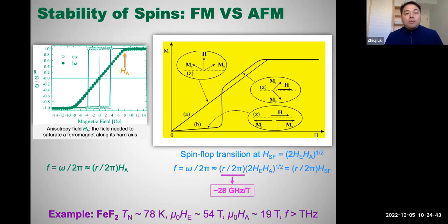If we look at this simple comparison between ferromagnets and antiferromagnets, for ferromagnets, the characteristic spin dynamics frequency, the so-called FMR frequency, ferromagnetic resonance frequency, is around gigahertz. It's simply gamma times H_A, where gamma is the gyromagnetic ratio, and H_A is the anisotropy field. But for antiferromagnets, because of the antiferromagnetic exchange energy, the resonance frequency is around terahertz.